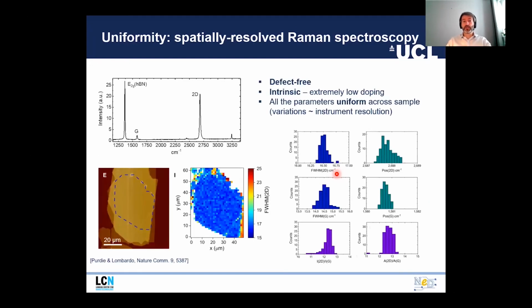We characterized the interface of the boron nitride-graphene-boron nitride heterostructure by Raman spectroscopy, and more importantly by transport. Raman spectroscopy reveals that the defect level is very small, as we would expect in exfoliated samples. We see a very large 2D over G ratio. And if we map all the Raman parameters, such as the full width at half maximum, the position of the peaks, and the ratio, we see that the variability is very small. We are very much within the resolution of the instrument. So we are talking about 1 cm^-1 as maximum variation.